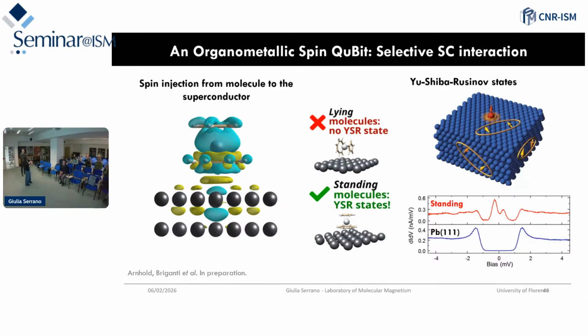I was curious because we have put a lot of molecules with Stefano and Fabio on metal surfaces, and when we put large conjugated ligands on a metal surface, we always invariably see some degree of metallization of the ligands together with the surface, and this influences very much the magnetic behavior of the center. Of course, you can treat the magnetic center as something isolated, weakly mediated by the surroundings, because you want to couple, for example, with your superconductor substrate. But is it always correct?